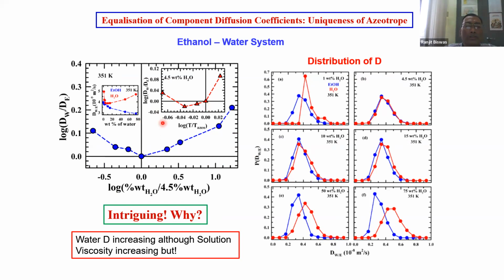What we are doing in this plot, you see that we are plotting the center of mass diffusion coefficients, and we are plotting the ratio of D_W, that is the water diffusion coefficient, by D_E, on a log-log plot, just to find the zero. So this means that the diffusion coefficient of water is becoming equal to the diffusion coefficient of ethanol at this concentration, which is zero, since the plot is percentage of water normalized by 4.5%. That means this is the azeotropic composition. So at this azeotropic composition, the diffusion coefficients of the components become equal.